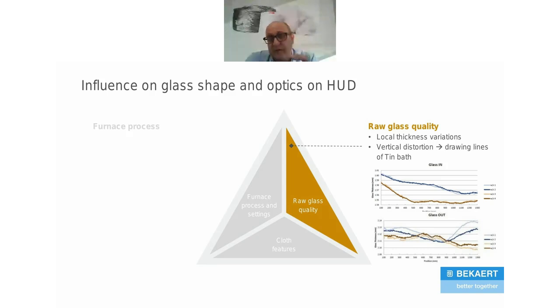So when this is varying too much, you can forget about having a very good optical quality on your laminated windshield. Because if you have this, the PVB will follow the result of the inner and outer glasses and will follow the thickness variations of the glass.